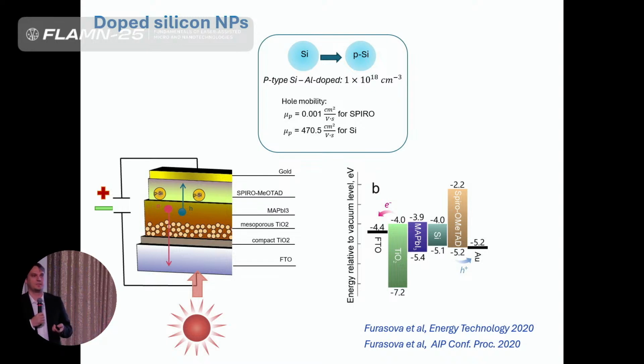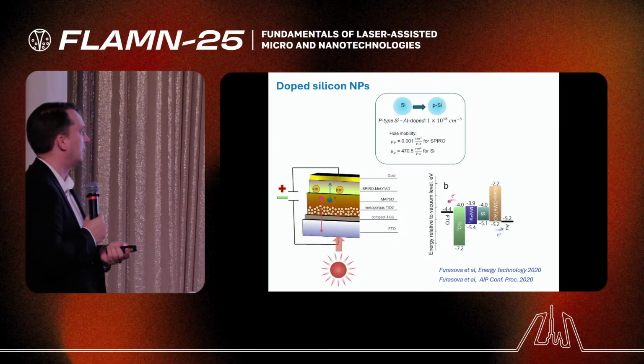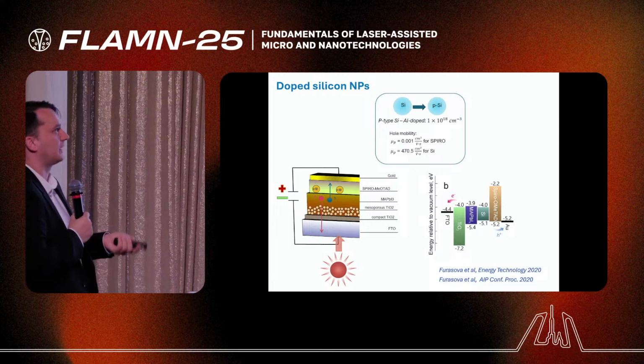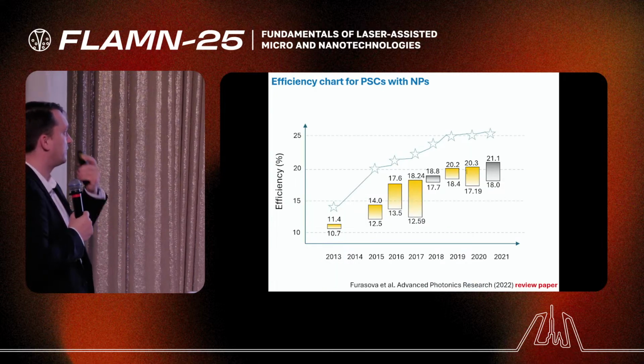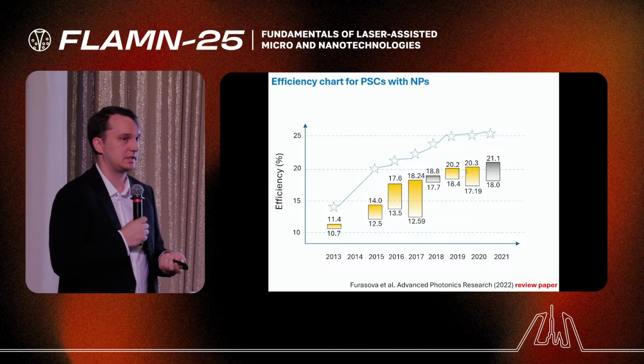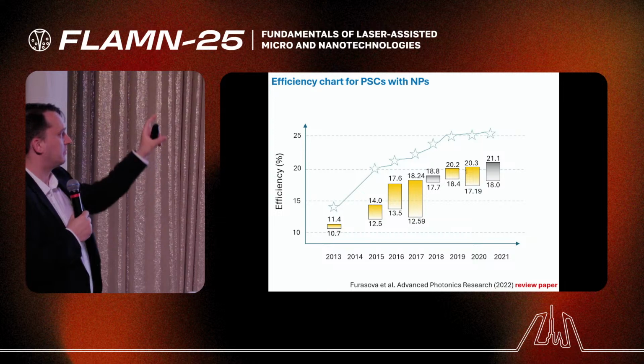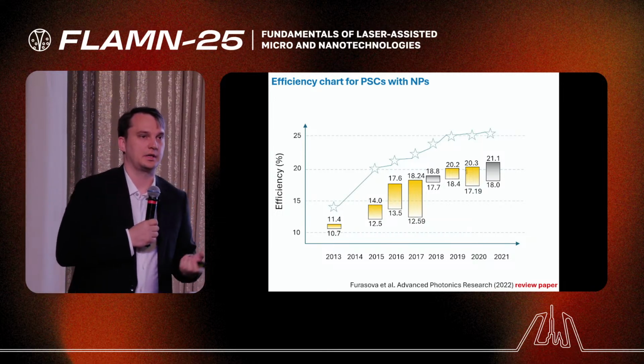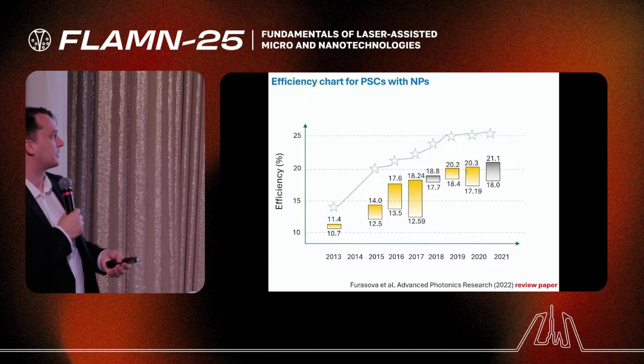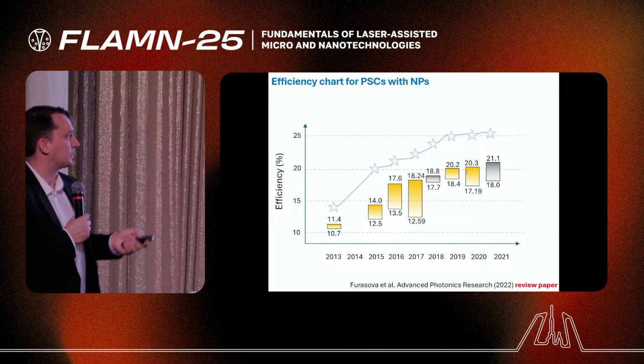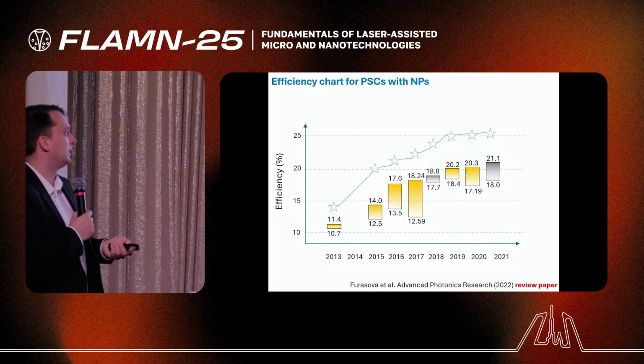We can use not only standard silicon, we can use doped silicon, and with doping we can play with mobility for carriers through such nanoparticles, and also improve carrier harvesting. So generally there is a chart of evolution in this direction: evolution of efficiency improvement in perovskite solar cells. You see the gray bars correspond to all the dielectric nanoparticles, and the yellow bars correspond to plasmonic. So far, improvement by dielectric nanoparticles has the best result in this direction.